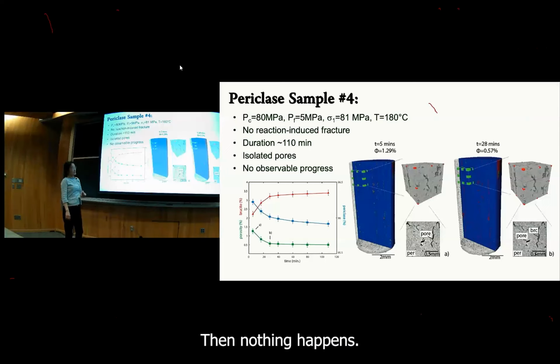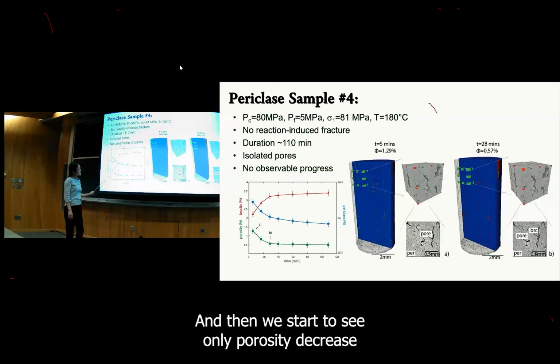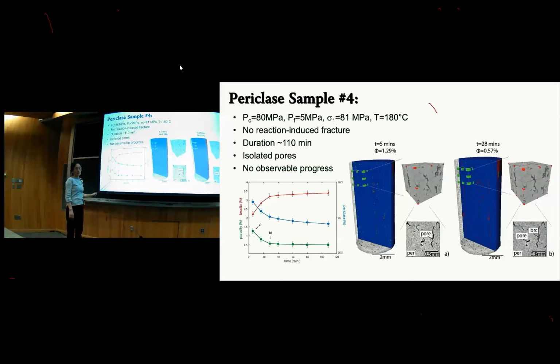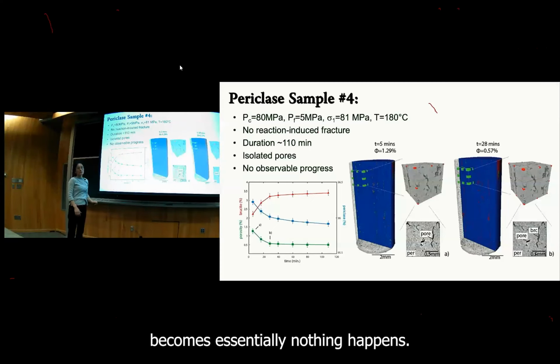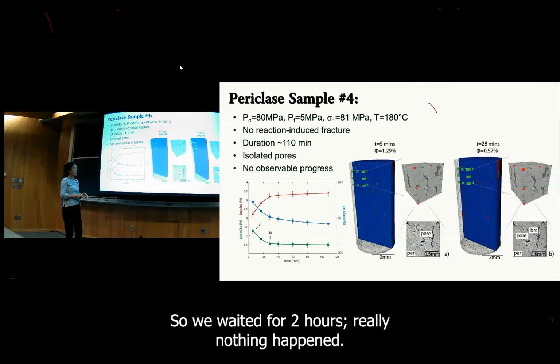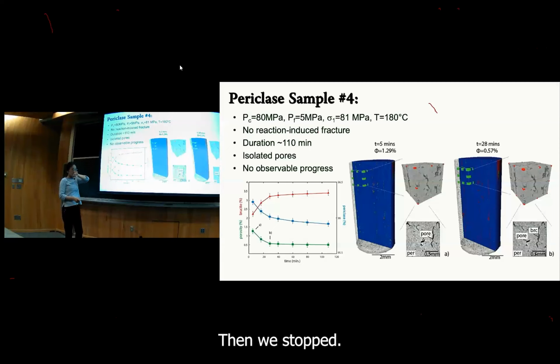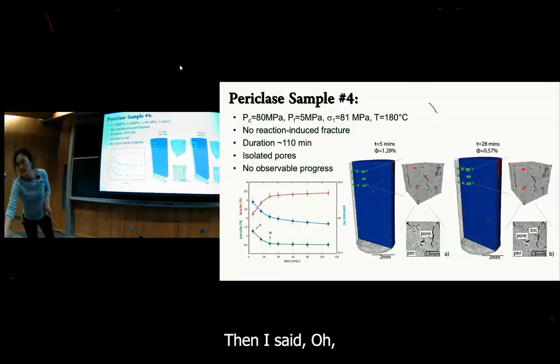Then nothing happened. At the beginning, it's very similar. There's not much. And then we start to see only porosity decrease. And then as it decreases, essentially nothing happens. So we waited 2 hours, clearly nothing happened, then we stopped. All right.